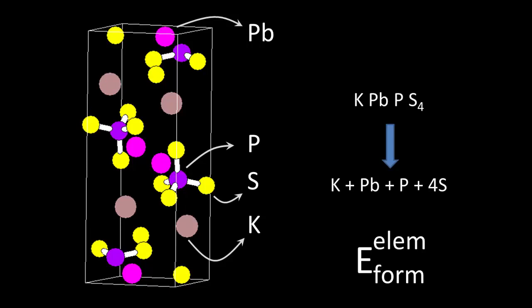So what will we calculate for all these quaternary Zintl phases? We will first geometry optimize them. So let vary the volume and the shape of the unit cell, and let vary the positions of the atoms in the unit cell to have the predicted geometry by density functional theory. Then we know the total energy for that optimized structure, and we will compare that total energy with the total energies from the individual elemental materials. So we take the potassium crystal, the FCC lead crystal, the phosphorus crystal in its ground state, the sulfur crystal in its ground state, and compare the energy with the one of this quaternary crystal.